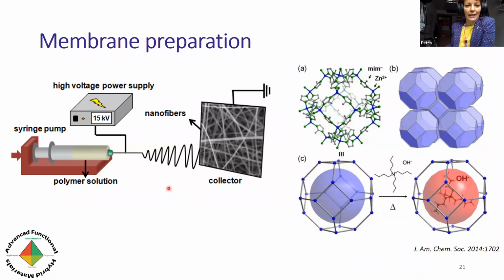Now, the way to do that is we prepare a polymer solution, and we add the metal organic framework, and we can electrospin it onto a collector, and as the solvent evaporates, the polymer will be drawn into fibers, sort of intertwined fibers that form a highly intercalated mat structure. Now, when we mixed this with metal organic framework crystallites, we hypothesized that it is possible that as the polymer fibers are being drawn, they would be coated with the metal organic framework. So that was step one, and I will show you the results in just a second.